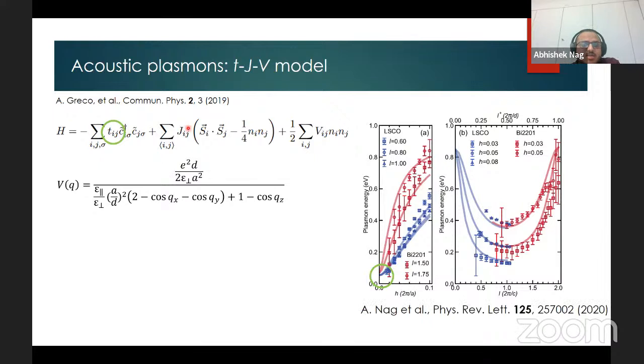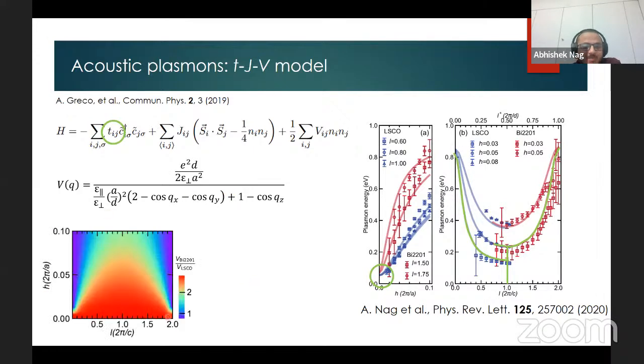You can find more comparison of the theoretical results and the experimental results in this work that was published last year. But before I stop, the one thing that I want to highlight is how sensitive these charge fluctuations are to the interlayer properties in these systems. As you may have already noticed, at L equal to 1, the plasmon energies in Bi2201 are much larger than LSCO. Now, if I plot the ratio of the Coulomb interactions between Bi2201 and LSCO in the HL plane, just using this formula, I get a map like this.